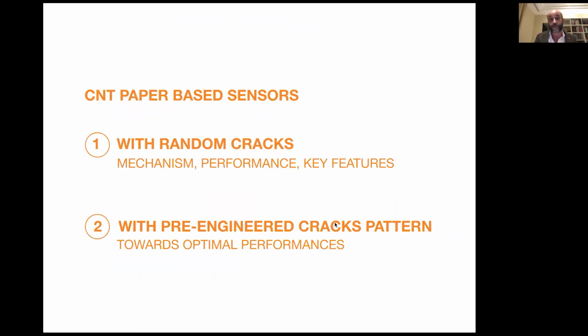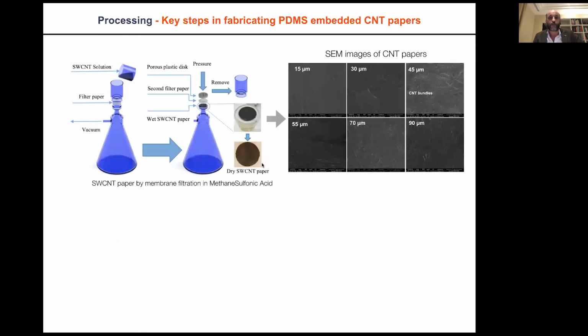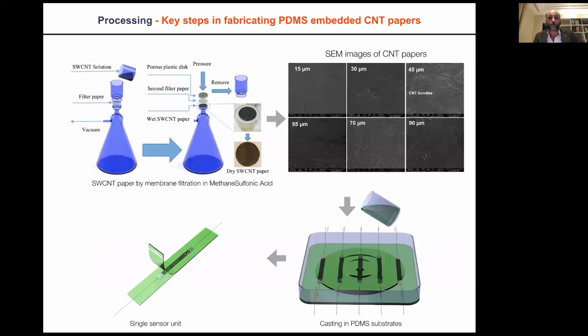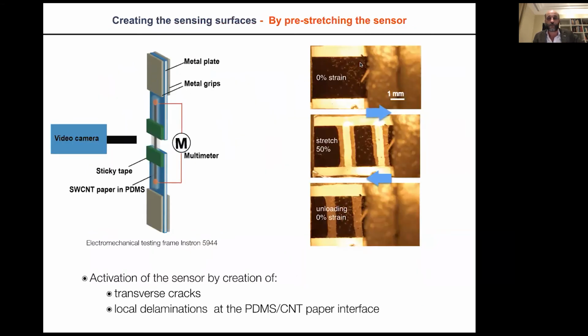So we did exactly the same thing, but we are using laminates with CNT papers, in which we are introducing cracks on purpose. Typically, the type of sensors on which we are working are going to look like this. That means we have CNT papers in which we pre-engineer cracks inside the CNT paper and embed it into a PDMS substrate. It's a CNT paper that is conductive, in which you activate cracks by pre-tension of the samples, cracks and local delamination. That means separation between the film and the PDMS substrate. And then following the activation, you can unstretch these sensors that are going to be used for strain sensing.